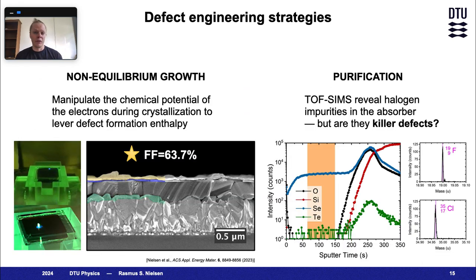Given the very low apparent carrier lifetimes, we have started investigating various defect engineering strategies. The first strategy is to lever the chemical potential of the electrons in our thin film during the crystallization, and thus change the enthalpic cost of formation of defects. So we are trying to grow the crystals outside of equilibrium. The result was amazing control over the surface morphology, as you can see from the cross-sectional SEM, and while the fill factor improved to a new record high 63.7%, the open circuit voltage remained unchanged.